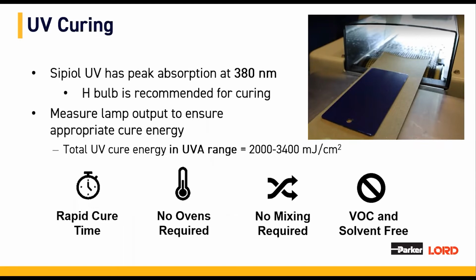In addition to equipment selection, UV energy can be controlled by exposure time, often by controlling conveyor speed, lamp height, and lamp intensity. Sipiol UV requires 2000 to 3400 millijoules per centimeter square of total UV energy to cure. With the appropriate energy, Sipiol UV will cure in seconds.